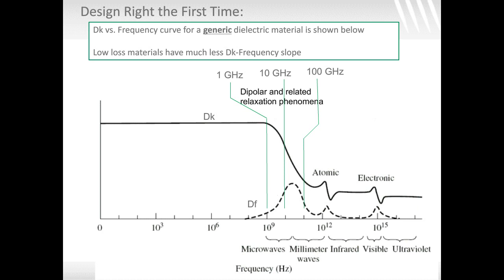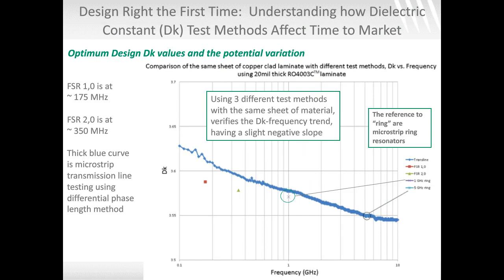And then just to give you kind of a feel for this, what I did was I did a study on the exact same sheet of material and used three different test methods, really trying to confirm that that trend is valid, that an increase of frequency means lower dielectric constant. The first test method I did is FSR, full sheet resonance, and that's actually testing the copper-clad laminate itself. And I did that testing to two different nodes, node 10, about 175 megahertz, node 20, 350. And sure enough, you can see on the chart here, the red dot and the green triangle, an increase of frequency means a decrease in dielectric constant.